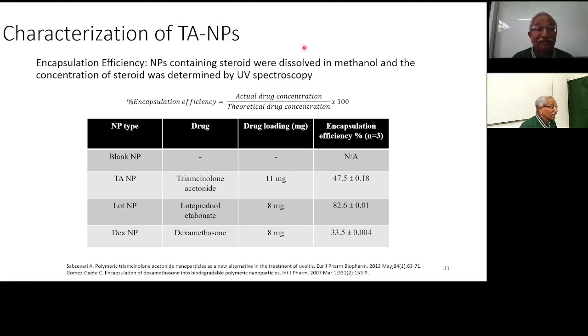So we tried to characterize the triamcinolone acetonide nanoparticles' encapsulation efficiency, how much drug really gets into the nanoparticles. We found that our drug loading can be 11 milligrams, which is 47.5% loading. So this will help you to understand how much dose you have to inject. And the drug loading for loteprednol etabonate was only 8 milligrams, while dexamethasone was 8 milligrams. So you can see 47%, 82% and 35%, based on the dose efficiency. And then we calculated the percent encapsulation efficiency: the actual drug concentration over the theoretical drug concentration, multiplied by 100.